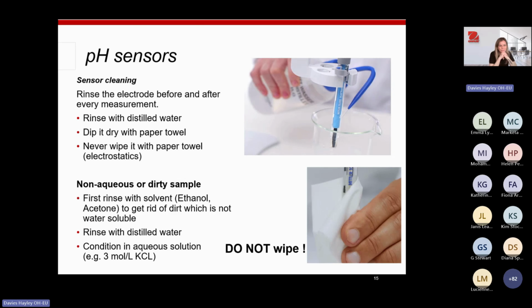pH sensors, so how to clean them. Rinse the electrode before and after every measurement, and before and after every calibration step as well. Always rinse with distilled water. You can use a wash bottle with distilled water and give it a squeeze over a beaker. And then dab it dry with a paper towel. I don't know why the slide says dip it, apologies. Never rub your electrode, never ever rub, because that would cause static and your readings will be all over the place because you're generating electrostatic charge on the electrode. With a paper towel, all you need to do is just dab it. Again, never rub it and never wipe it, just dab it.